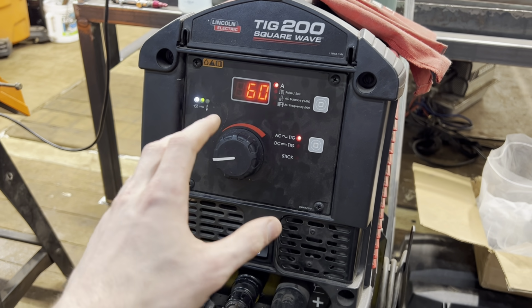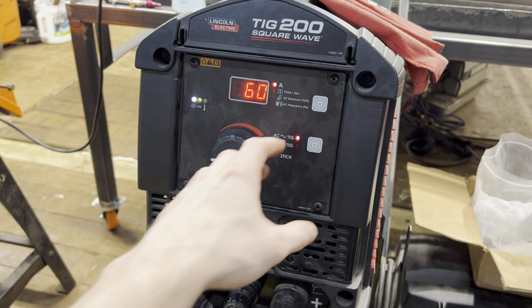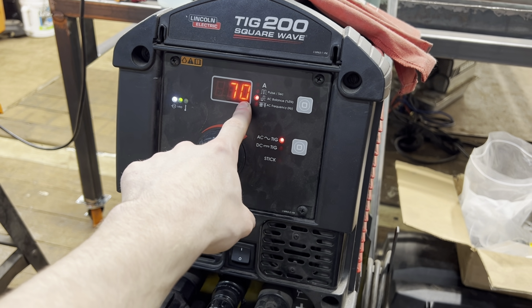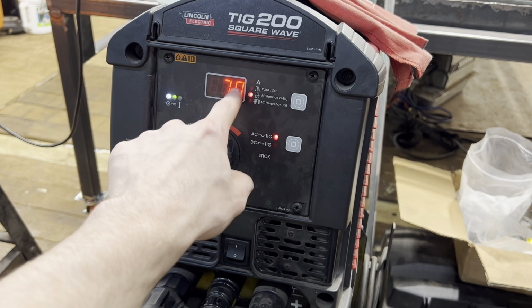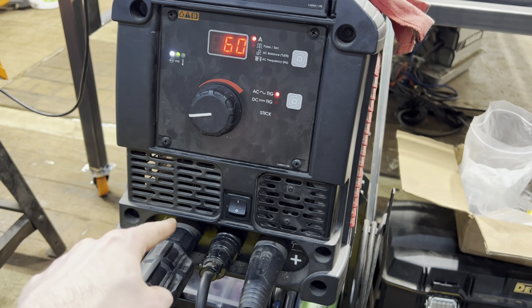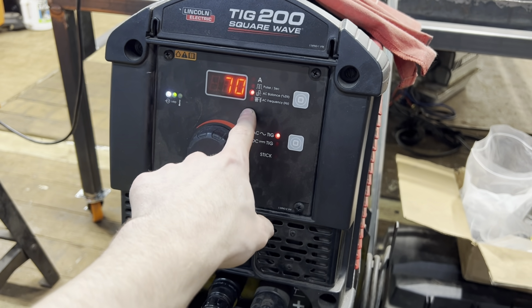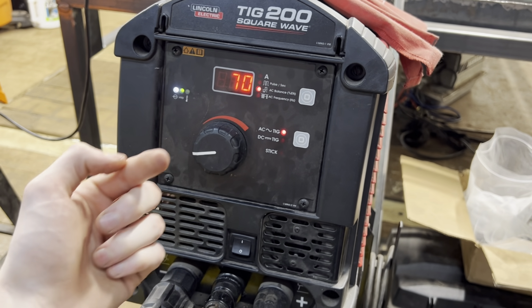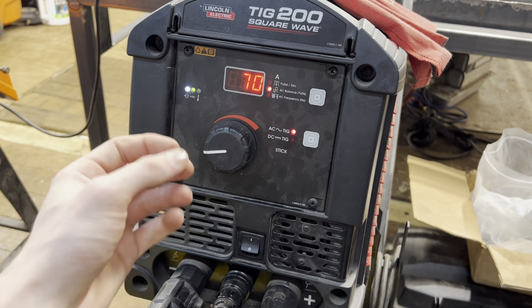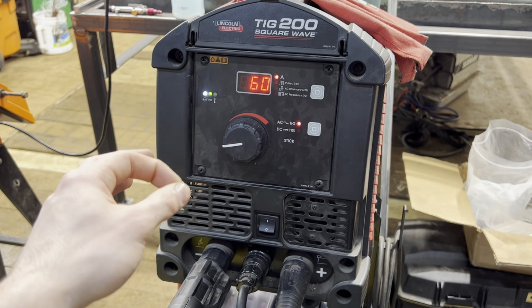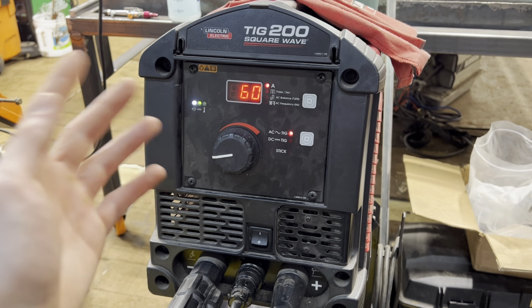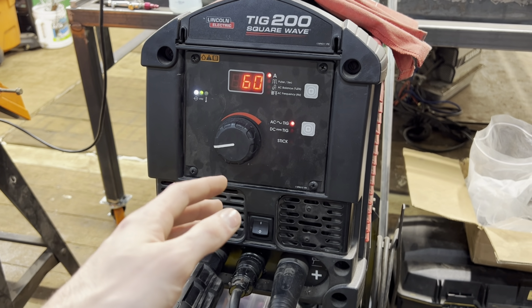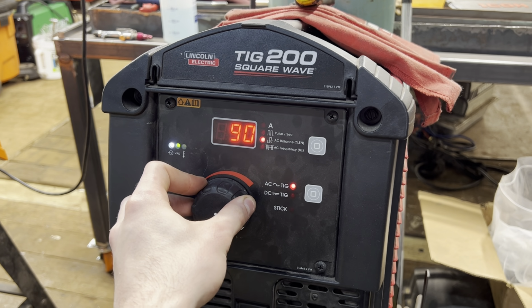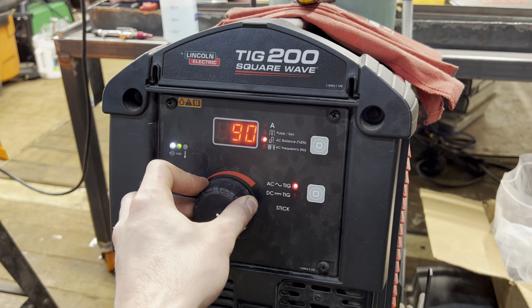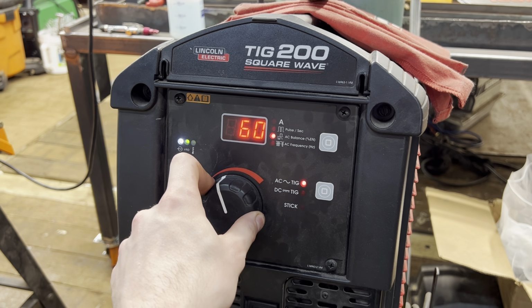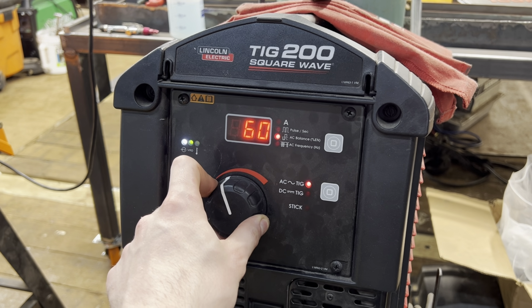If you've ever heard of someone balling their tungsten for aluminum, the reason that that happens is because now instead of being on DC and having all of your current going out of the tungsten, now you have a percentage of your current coming towards the tungsten, and the force of that current flowing towards the tungsten rounds that end off. The reason for changing that setting is to have more cleaning or more penetration. When you have more electrode negative, you have more penetration and less cleaning. When you have less electrode negative, you have less penetration and more cleaning.